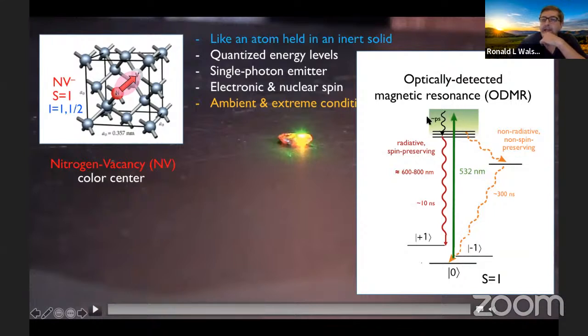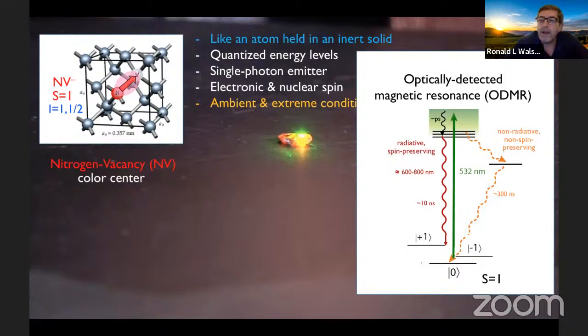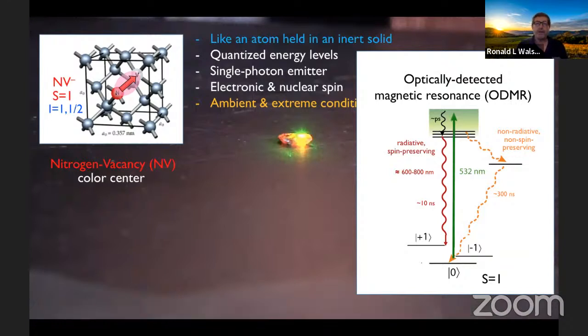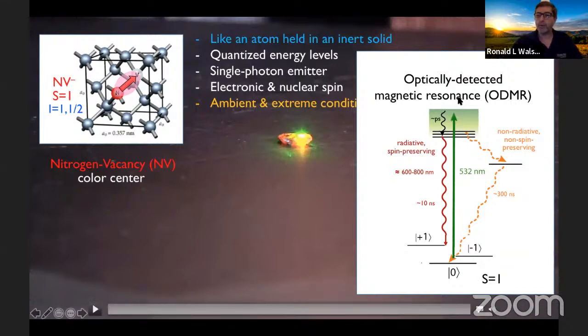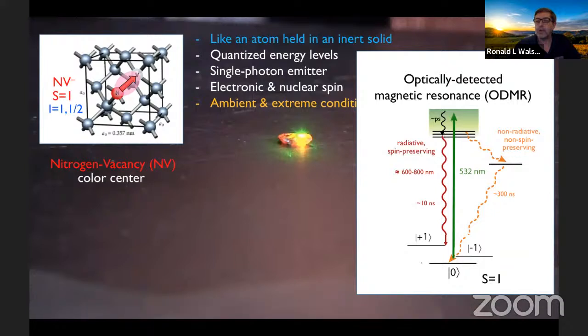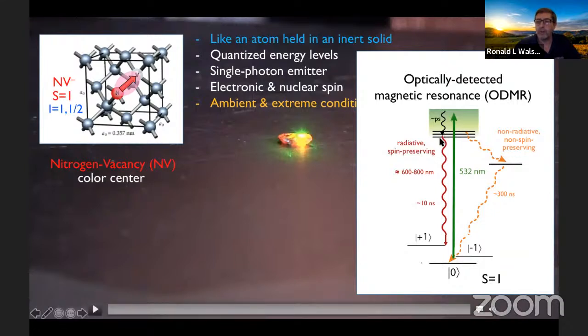Above in green is the electronically excited states. There's many of these states, but they're strongly coupled to each other by phononic interactions. And the ground and excited states are split by an optical transition, so that if you illuminate the NV with any reasonable optical color from the yellow to the near blue, but for example, green, the NV will tend to absorb green light. Within a picosecond, it will rapidly decay down to the bottom of this vibronically excited band of states. And then one of two things will happen to the NV. It'll either emit a red photon and undergo fluorescence.